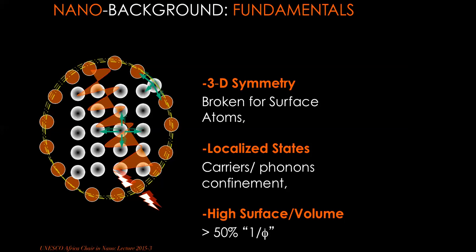In addition, if you have a gold particle, a metallic nanoparticle, you have free electrons, and these free electrons cannot leave these nanoparticles. It's as if they are in a quantum well. And all of us have done the Schrodinger equation and the quantum well type problem. This is exactly what you have to see here. So you would have the 3D symmetry, which is broken, like we said. Many atoms on the surface will not vibrate as in the bulk. You have localized states because you have electrons which cannot leave these particles. They are stored in this well. So therefore, optical properties are very sensitive to that, and you will see that.